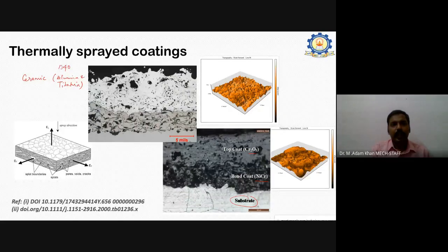A40T means alumina with 40% titanium. Okay, alumina having 40% titanium, 60-40 ratio. So ceramic, pure ceramic as one coat, and the second one is called a two-way coating method. One is bond coat, another one is top coat. For the bond coat I used nickel chromium. For the top coat, I used chromium oxide, Cr2O3.